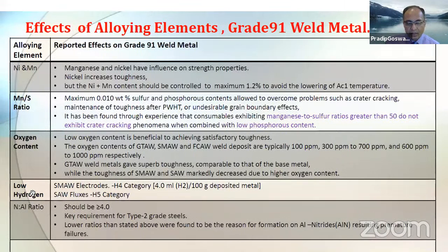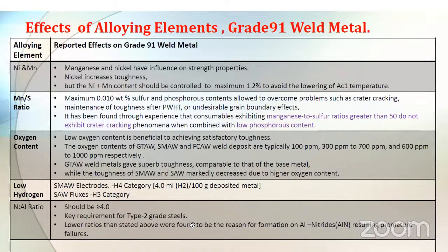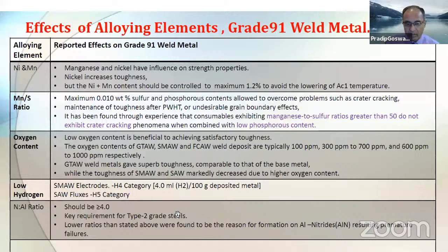Now, low hydrogen is a must, because this steel is very much prone to any form of cracking. Hydrogen cracking is a very common consideration. So H4 category for shielded metal arc welding is a must. And for submerged arc fluxes, also the wire flux combination, it should typically be H5 category. The nitrogen to aluminum ratio should typically be 4 or more. And this is a key requirement for type 2 grade steel. As I mentioned earlier, that's the grade which is more needed for elevated creep strength requirements. It's also stated that lower ratios than stated above were found to be the reason for formation of aluminum nitride, resulting in premature failure.